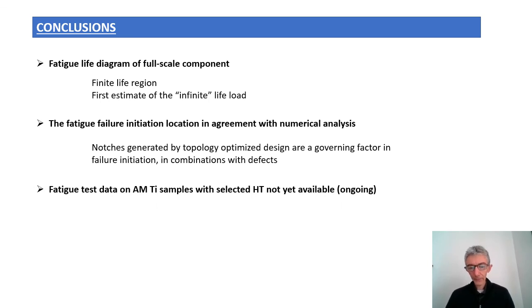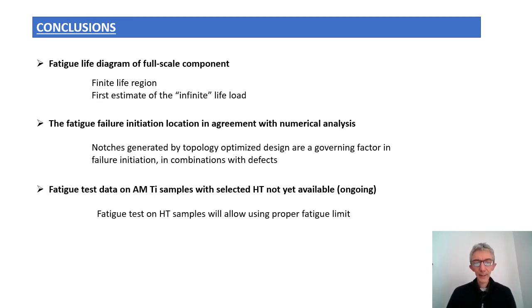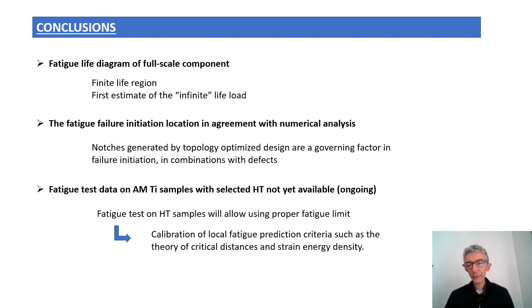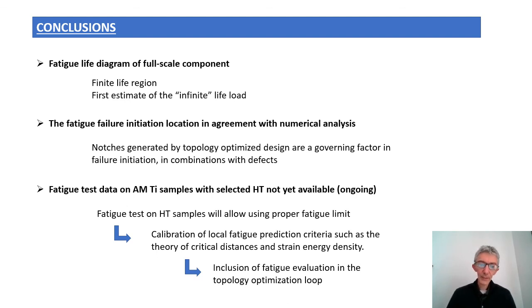And finally, of course, fatigue test data on AM titanium samples are needed with a selected heat treatment. They are not yet available, but the tests are scheduled very soon. And with this data, we will be able to use a proper fatigue limit in the design of the conrod, and hopefully to calibrate local fatigue prediction criteria, such as the theory of critical distances and strain energy density. And in the end, we would like to include fatigue evaluation in the topology optimization loop.